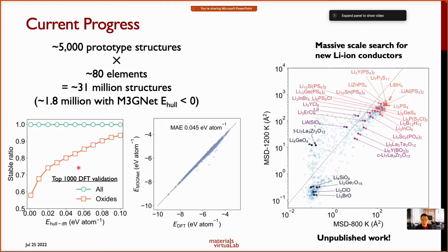and we show that actually the agreement is pretty good. In fact, the hit rate is very good. We can get about 80 to 90% hit rate if we choose a cutoff of about 50 meV per atom as a stability cutoff. Okay, we have also used this data to conduct what we call a massive scale search for new lithium superionic conductors.